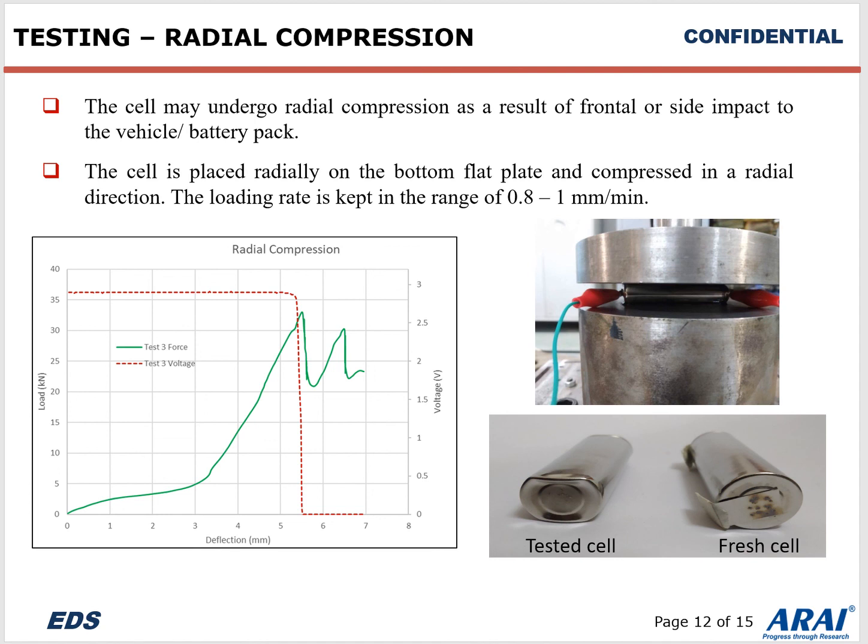After that, there is a sudden drop in the force value. At the same time, we can see that there is a drop in voltage. So that means the voltage drop is a result of rupture, which results in a short circuit. This load versus deflection curve is a very important one, and it will be used for correlation with our simulation as well.